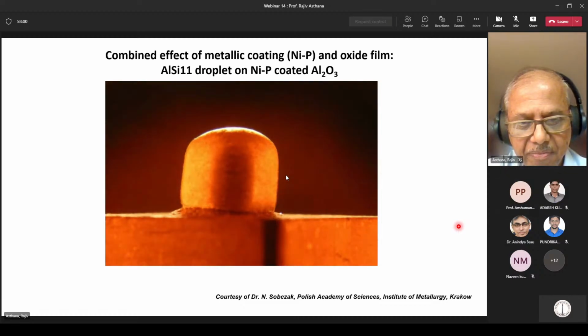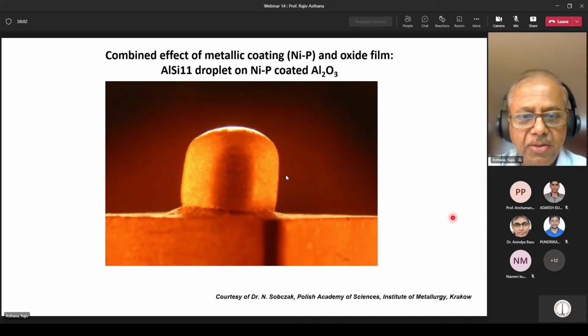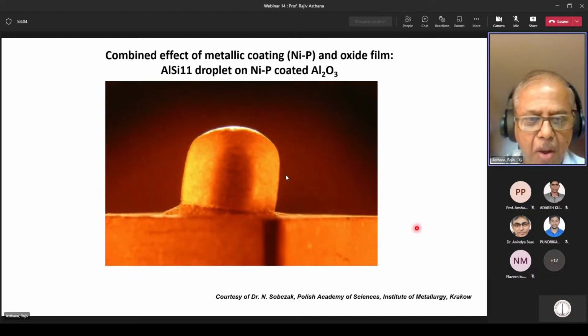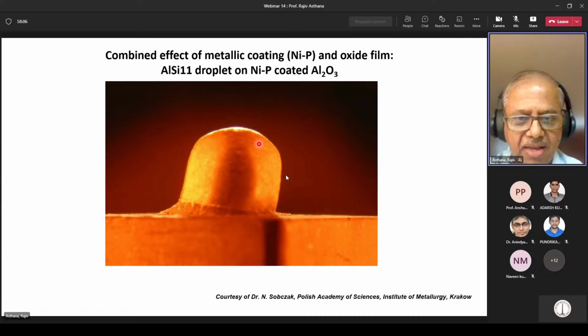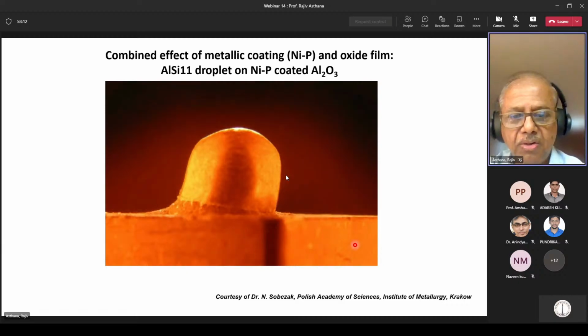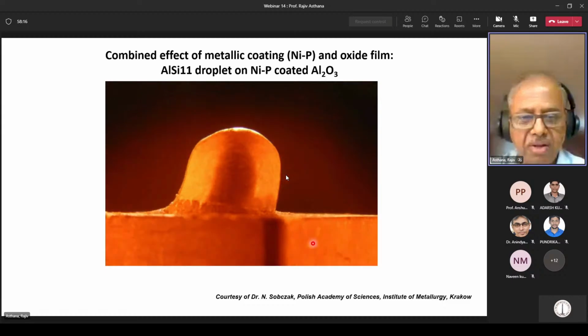Look at how this 2 millimeter droplet is spreading, and this oxide skin is preventing the spreading of the liquid underneath. So when you have situations like these, if you measure the contact angle without understanding what is happening on the surface, you get incorrect data.